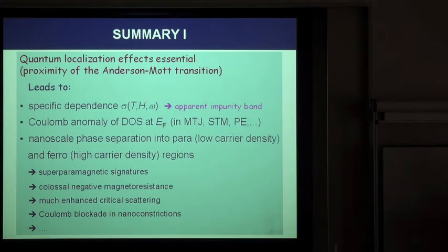So using the Drude-Boltzmann model is very dangerous in this particular case because there is strong renormalization. Actually, to say that this effect is dramatic, it is enough to say that exactly this quantum effect makes the resistance at some point go to infinity. So this renormalization of conductivity or resistivity is not just a small effect, but brings resistivity from a finite value to an infinite value. So the importance of this quantum correction cannot be underestimated.